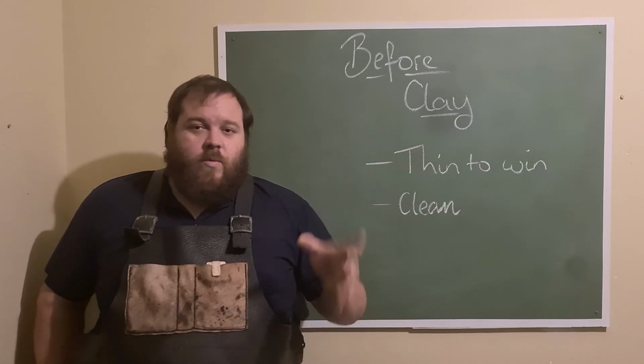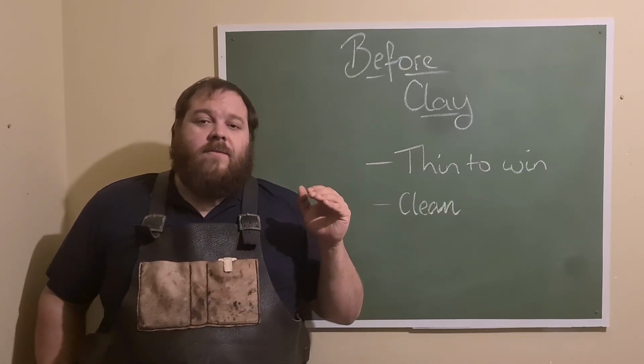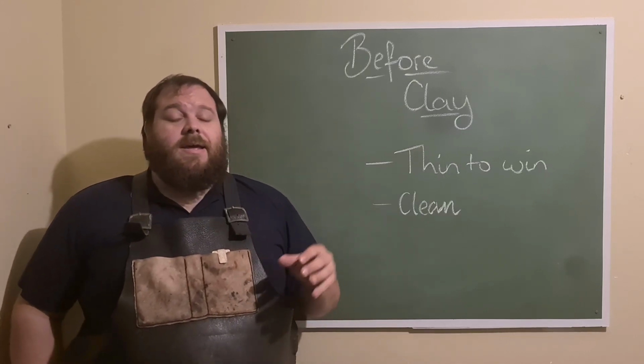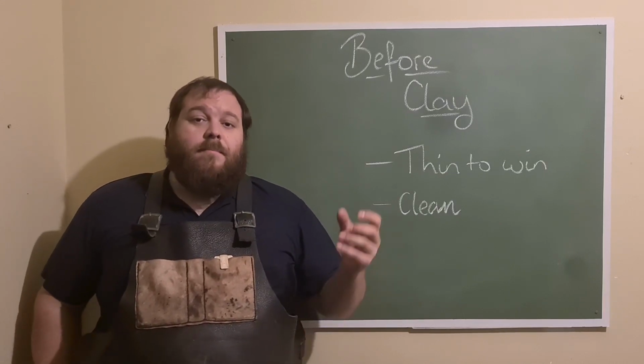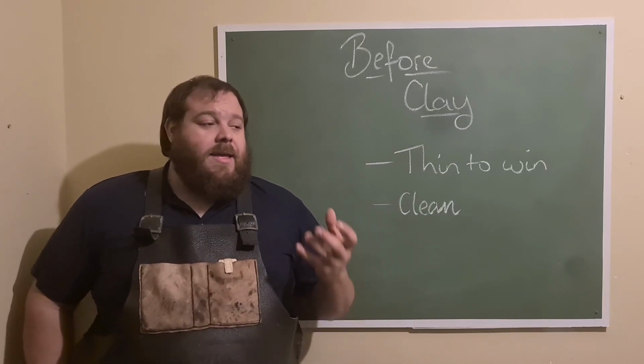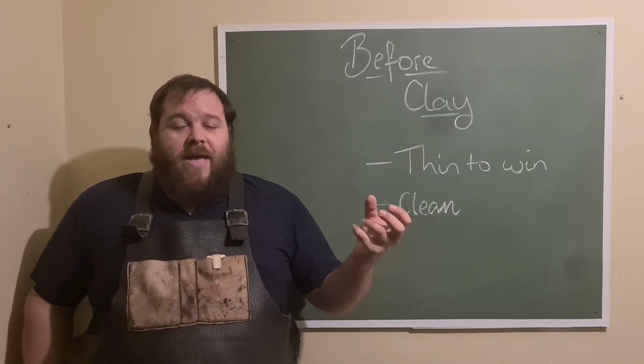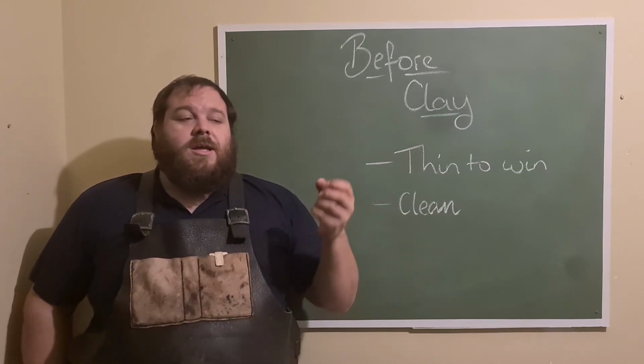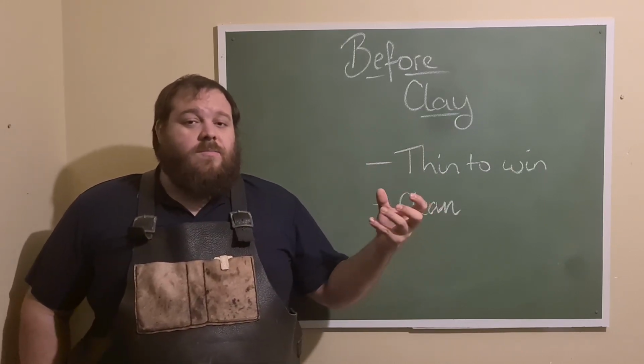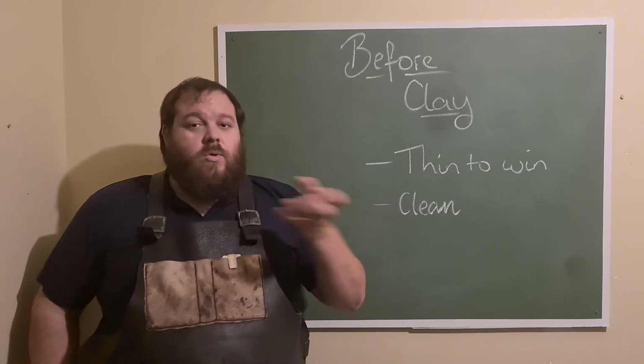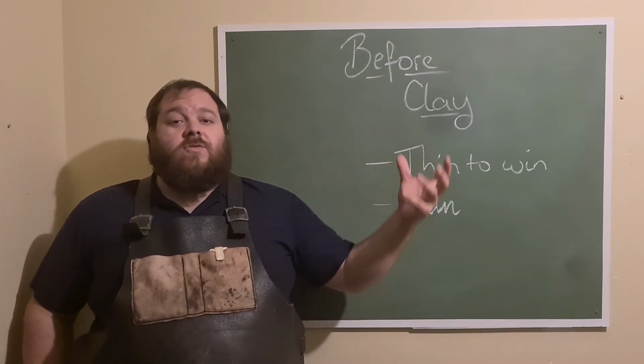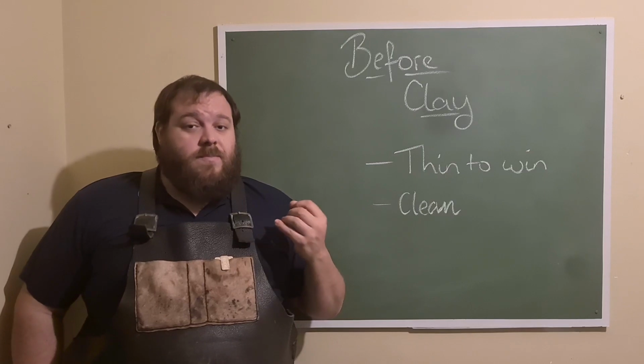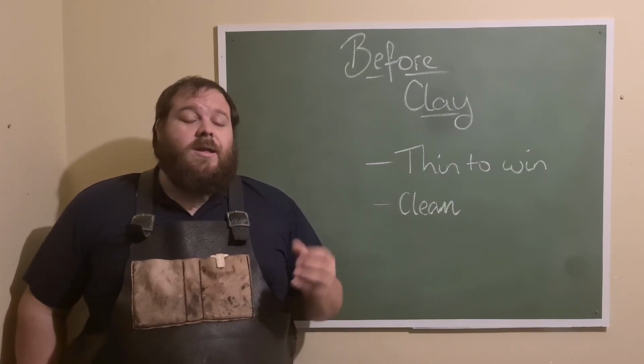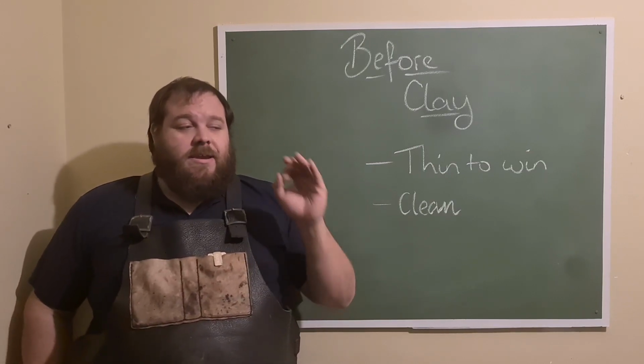If you have squiggly lines everywhere, if you have various thicknesses in your blade, that will affect the Hamon. Remember, mass being your main enemy. If you have large sections of edge and small sections of edge, then the larger sections are going to hold on to more heat than the small sections, and they're going to cool unevenly. And this is true of even when you're heat treating a normal blade, but in Hamon it's specifically really, really important to get everything nice and clean and right.